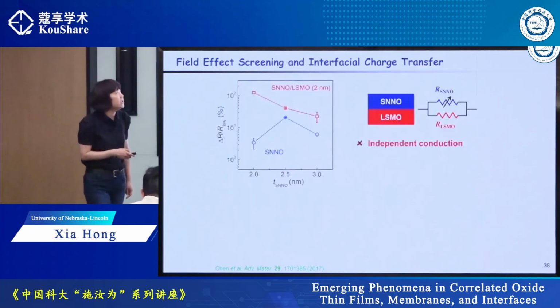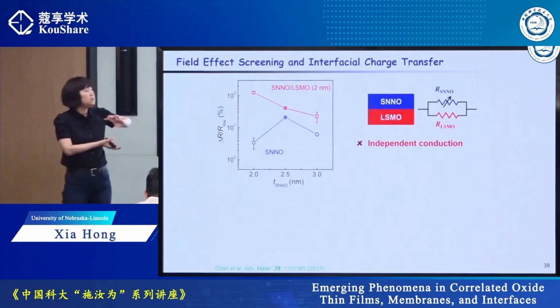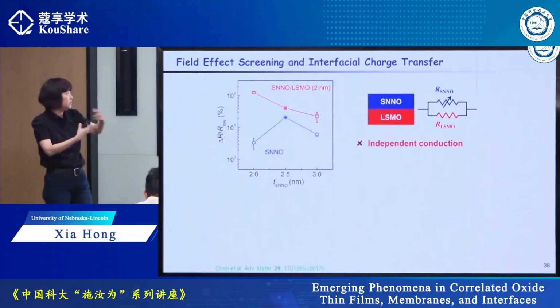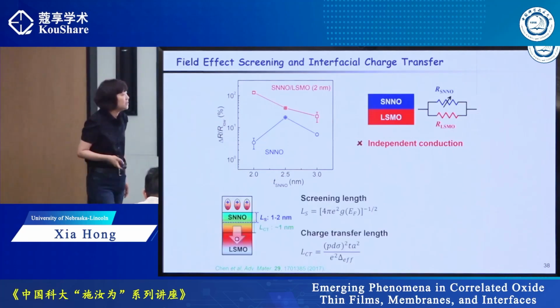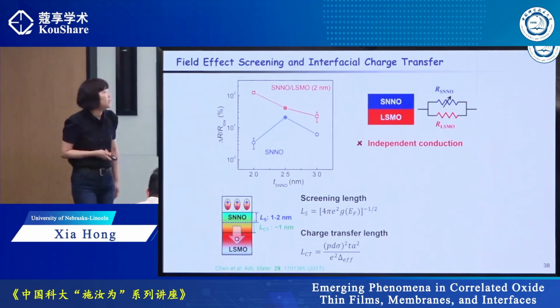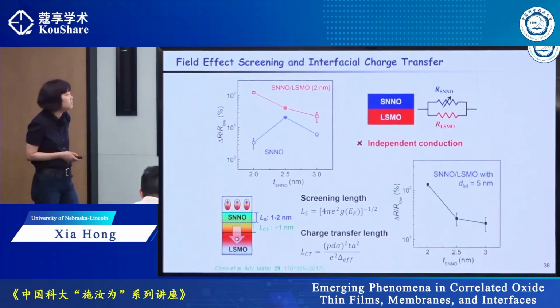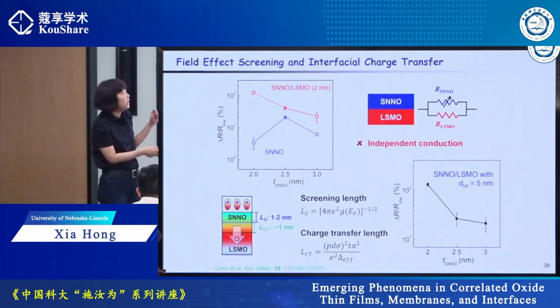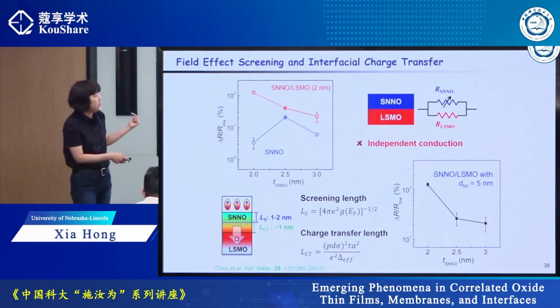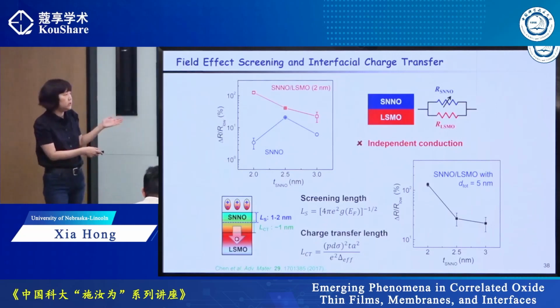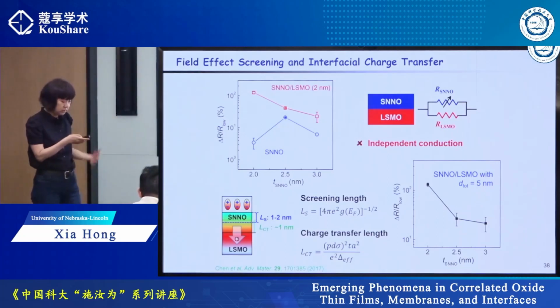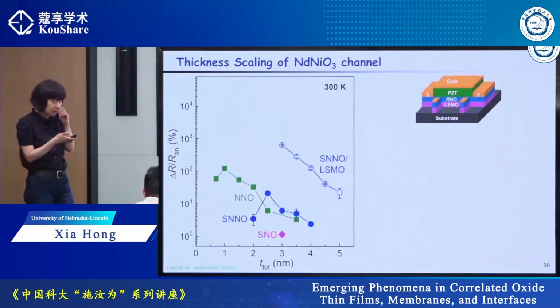So what that tells you is I cannot treat the SNO and LSMO channels as parallel, independent conduction paths, right? There must be some synergy at the interface. And this kind of enhancement has been observed at all thicknesses. If you have SNO 2.5 and you insert the additional channel, the effect becomes smaller. That testifies to our hypothesis that indeed we have interface charge transfer, and we could try to probe what LSMO layer thickness would give you the largest boost. It's about 2 nanometers, which is comparable with the calculated charge transfer length. So that also supports that our scenario is valid.